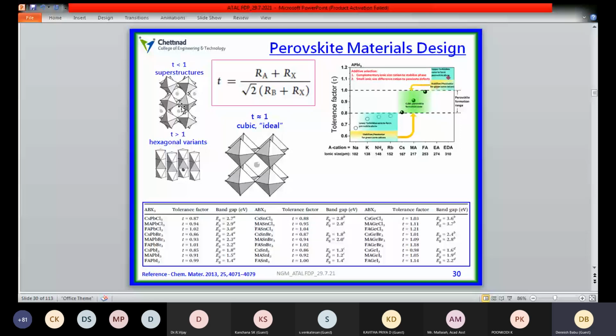So in this table, people have listed various tolerance factors and the optical band gap values which they have identified for particular materials, including cesium lead chloride and methylammonium lead iodide. Some materials are not able to produce the band gap value due to the high tolerance factor. So that must be considered. The tolerance factor must be approximately equal to 1. Then only that perovskite will be useful for PV application. Not only PV, other photovoltaic and optoelectronic device applications also.